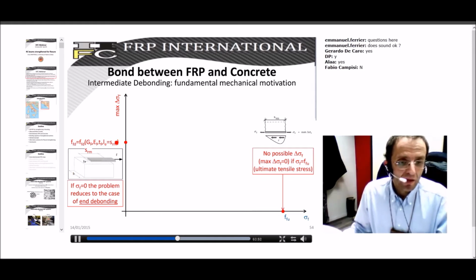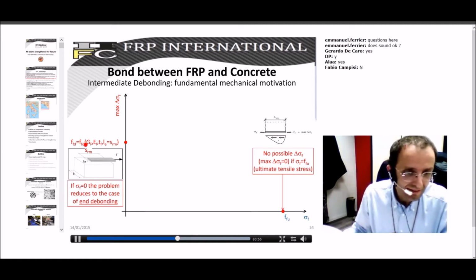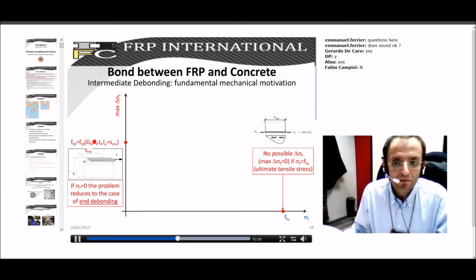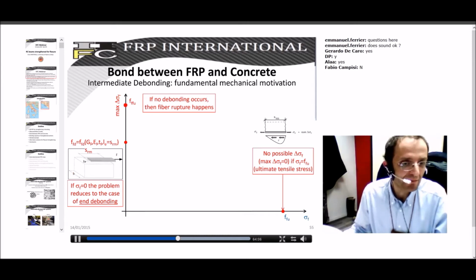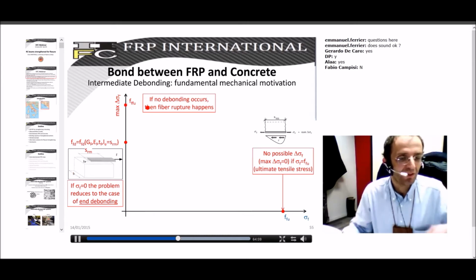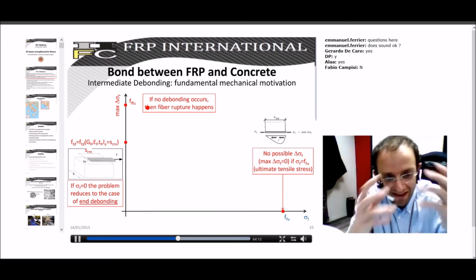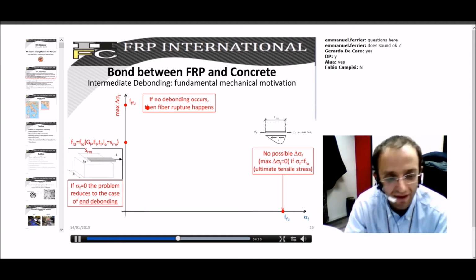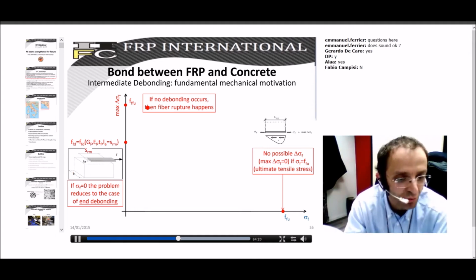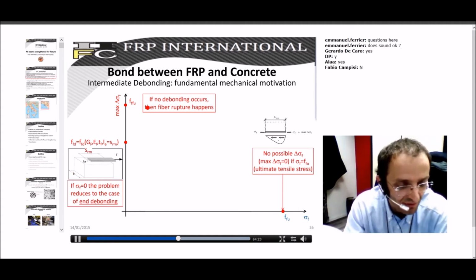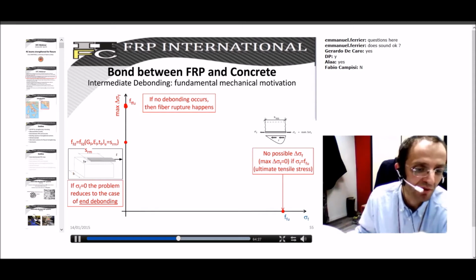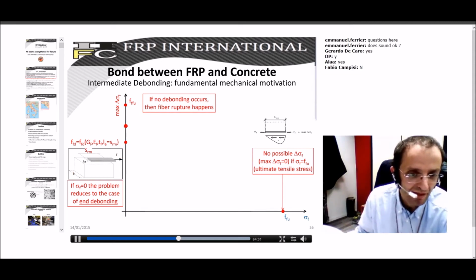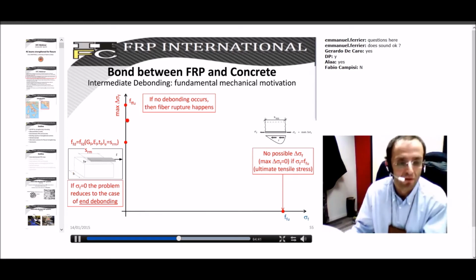Of course, if the interface is a very strong one, you should consider that the maximum force you applied here can never be bigger than the maximum strength of the composite. This is the ideal situation. It's not a realistic one, but the ideal situation in which you have a pull-out stress which fails due to axial rupture of the strip. So this is really the maximum possible value you can obtain. Up to there, if the rupture occurs for a lower value, you have debonding. Here you have potentially not debonding, but axial rupture. It's an ideal case, but you have to take this into account.